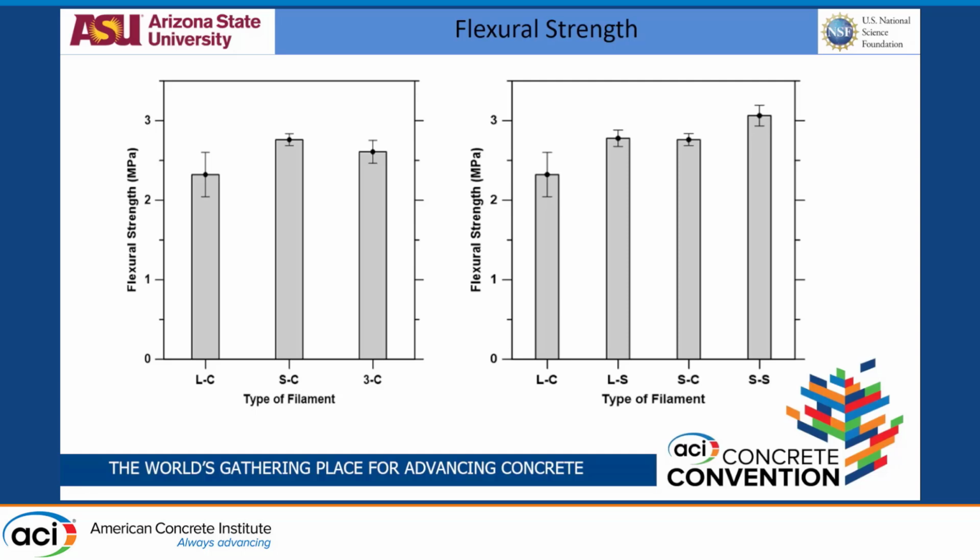This filament that I did not show you here is a 3-shaped filament where we did not alter the direction of the course. We discontinued it from the start because at the point of joint there's a higher material deposition on the corners, resulting in a non-linear kind of print, with very high material being deposited where the courses meet. With an alternated course, the print is smoother, with the same cross-sectional area. So we focused on the S-shape more than the 3-shape, but having something similar in the 3-shape would also have helped us significantly in getting the flexural strength.